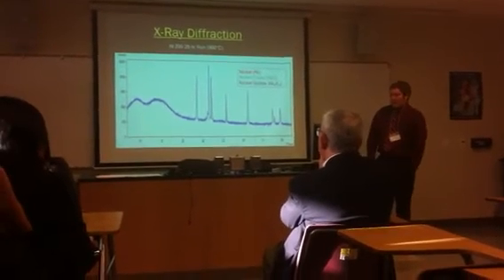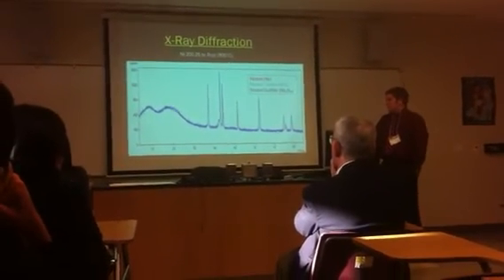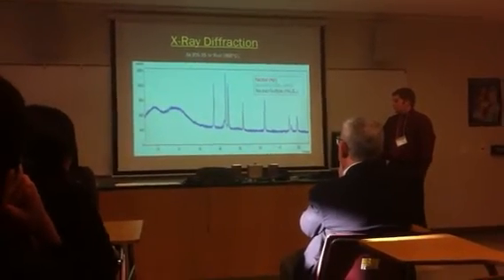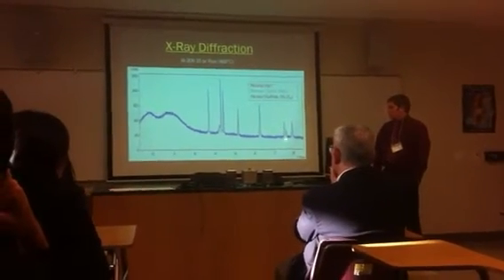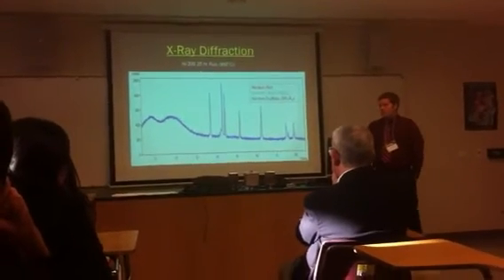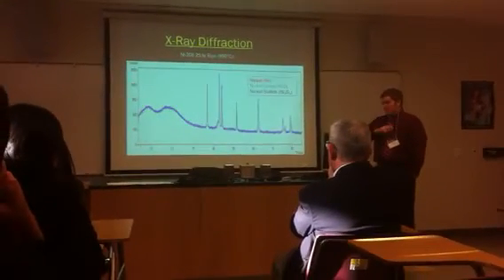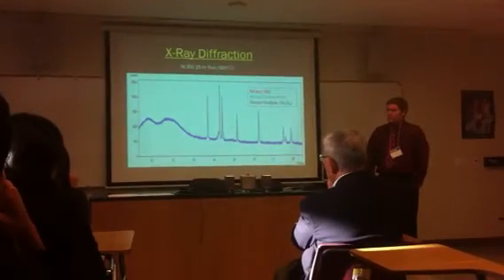And here's a nickel 200 sample after a 25-hour run at 900 degrees C. And as you can see, we still have our nickel substrate showing up and our nickel oxide. But now we have some peaks showing up that are characterized by this nickel sulfide material. What we're hoping to show is that as our hours increase, we'll have higher and higher peaks of this.